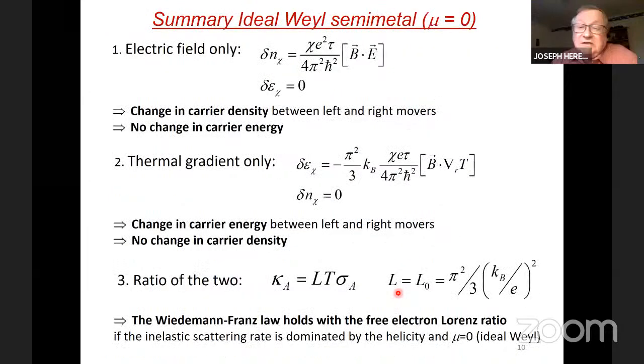To summarize, in an ideal Weyl semimetal, an electric field only gives you a term that's proportional to B dot E, but no change in energy. And a thermal gradient only gives a term that's B dot grad T, but no change in carrier concentration. So we're going to look particularly at this term in our experiment.